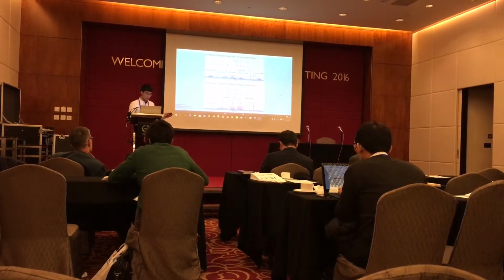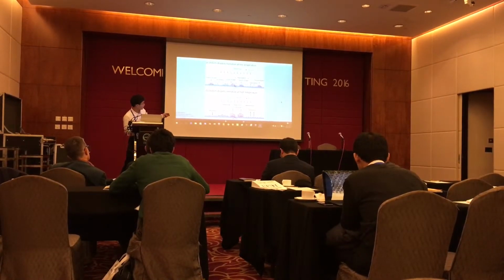At high substrate temperature, the phenomena of surface diffusion, aggregation, and disruption are happening, and the probability of these phenomena is larger than at a lower substrate temperature. So relatively big dot size and lower density of nanodots will form at high substrate temperature.